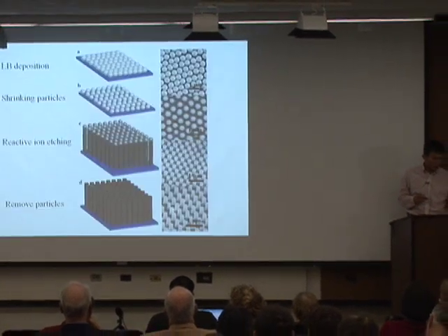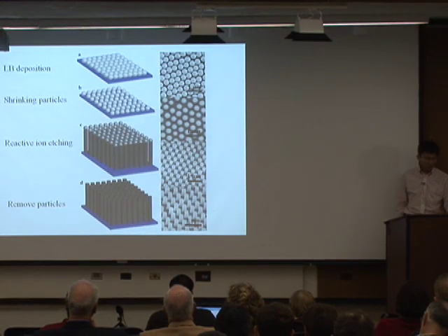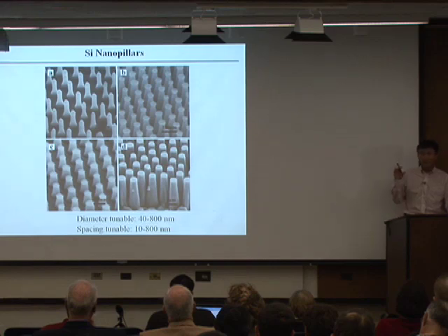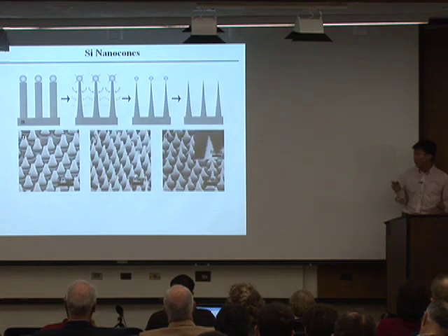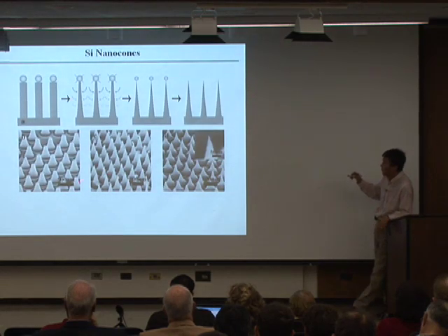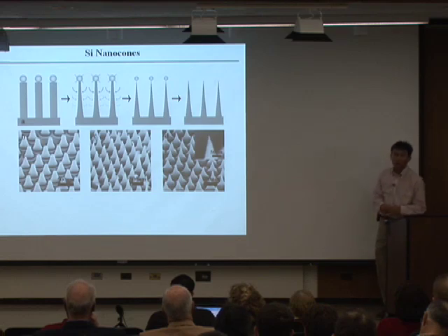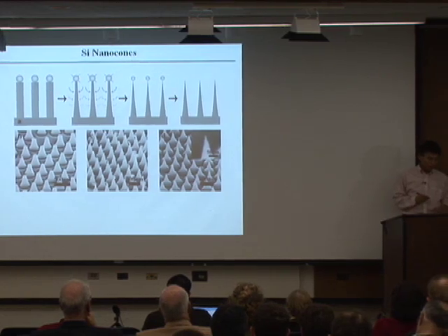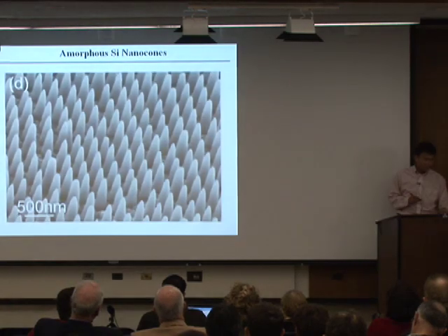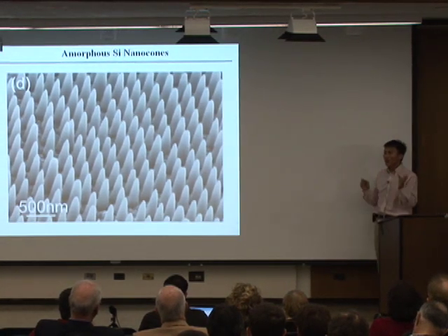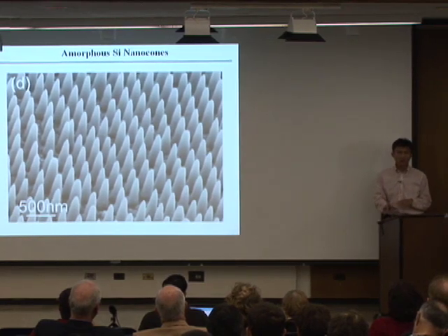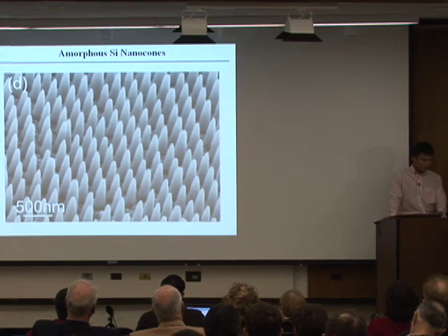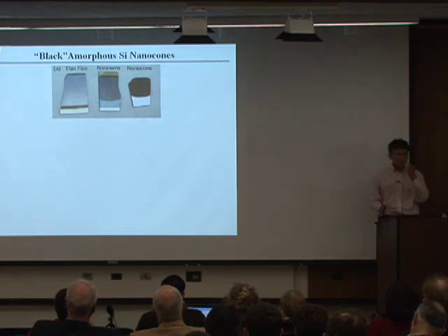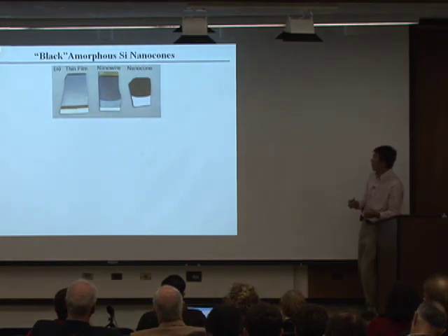So if you use that as an etch mask, you can etch these very nice pillars. Depending on how you do it, you can etch different sizes, different spacing, and you can even control the shape, going from a pillar to a cone. That looks fairly interesting. Well, this is on single crystal silicon. And then one of my graduate students, Jia Zhu, said, well, let's look at amorphous silicon. So he can etch the amorphous silicon also to form a similar type of structure, a nano cone. But what's exciting is just by eye, you see something dramatic happen. So this really motivates us to go into the area using this structure for solar cells.